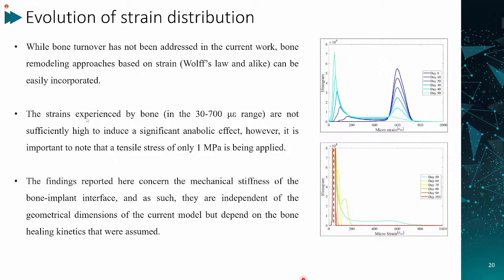However, it is important to note that a tensile stress of only 1 megapascal is being applied. So if you apply a different force or a different type of force, you may get a different result, and this result may induce bone remodeling or trigger bone damage. So the findings reported here concern the mechanical stiffness of the bone implant interface, and as such, they are independent of the geometric dimensions of the current model, but depend on the bone healing kinetics that were assumed.